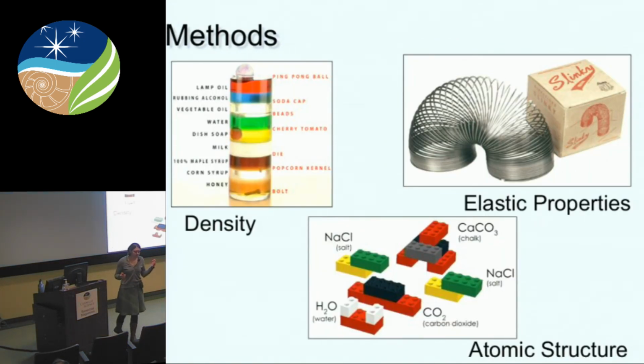Okay, so if I'm interested in measuring the properties of amorphous materials at high pressure, like I told you earlier, a lot of times traditional methods developed for crystalline materials like X-ray diffraction generally don't work very well. So I've had to use some novel, recently developed techniques, and today I'm going to focus a lot on density and the elastic properties, but I've also done some work on trying to measure the atomic structure in these materials to see if we can tell if network flexibility is active, and then also what the influence is on things like seismic velocity of the presence of silicate melts.